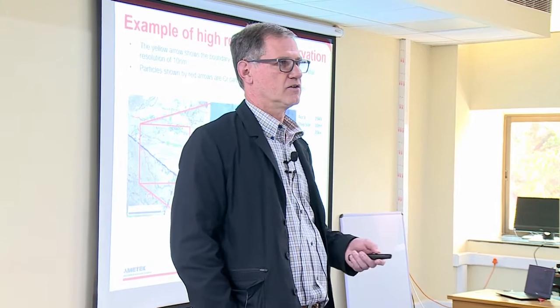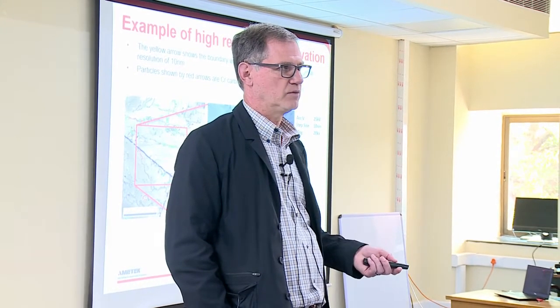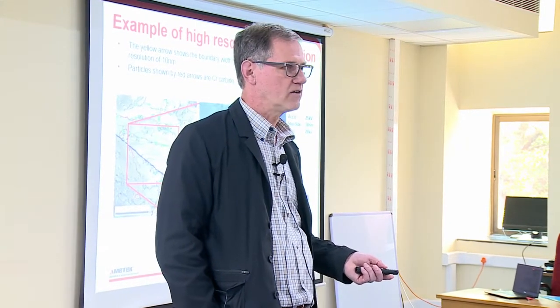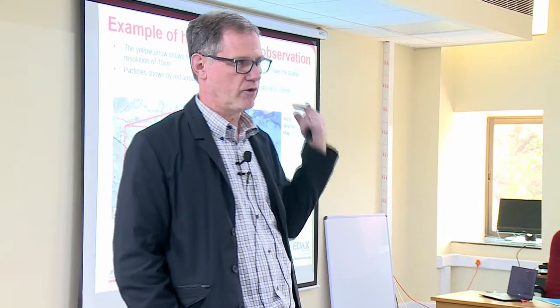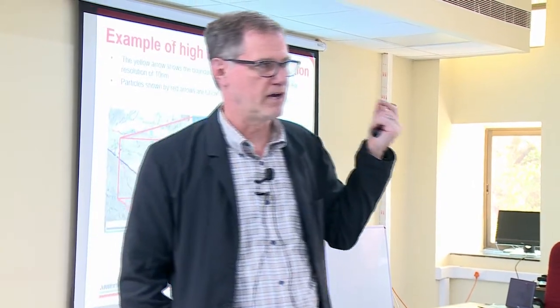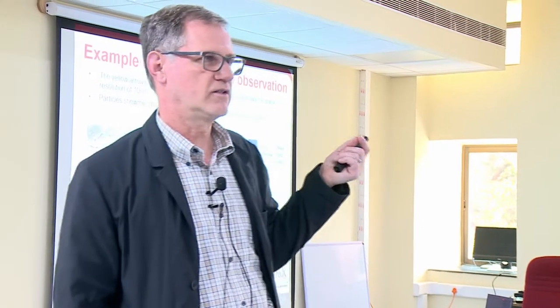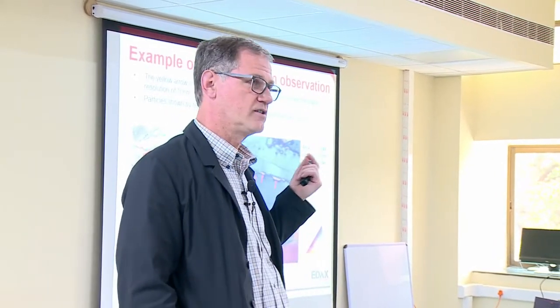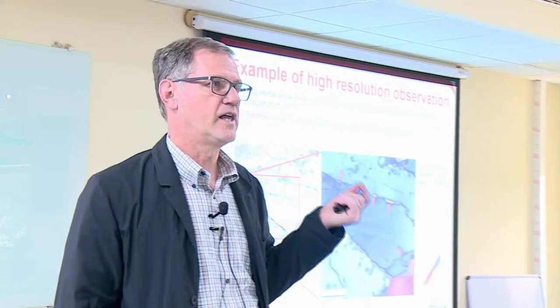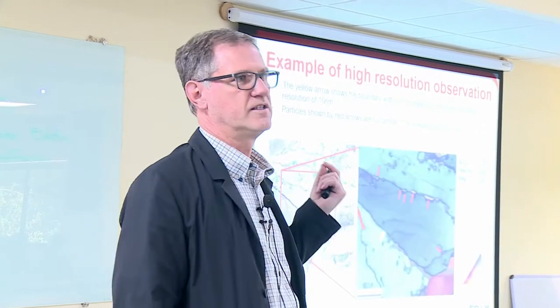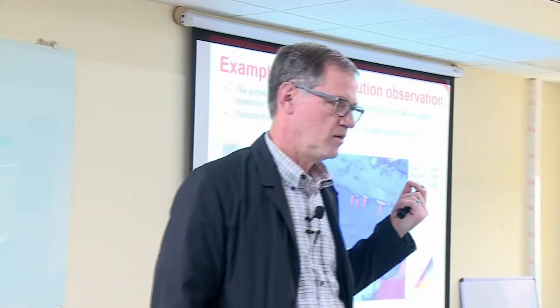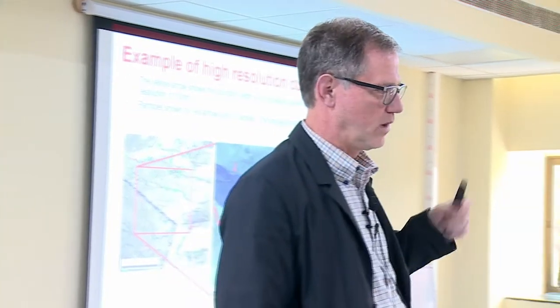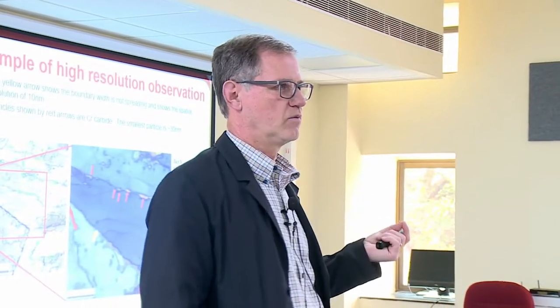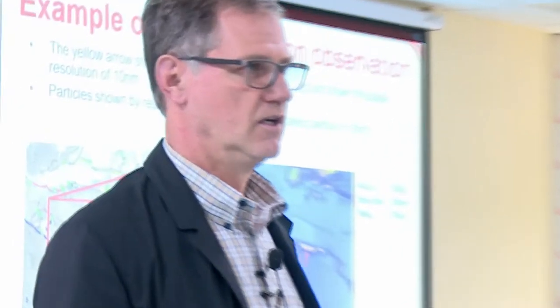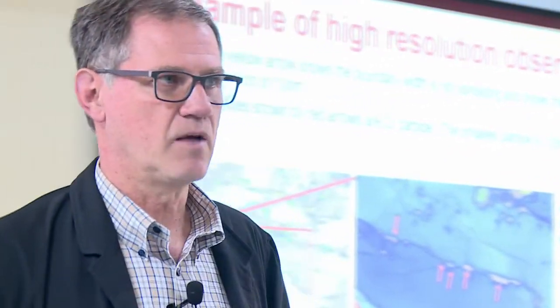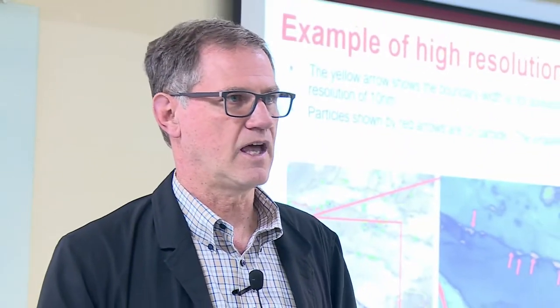There are a lot of signals coming off the microscope. With EBSD, we primarily are looking at elastically scattered electrons, or the ones that are forming the patterns, although we know now better the distribution of electrons and the energies that we're measuring, and there is some inelastically scattered electrons that help form these images. But the images themselves, in terms of the way we interpret them, we basically assume we're only dealing with the elastically scattered electrons. The other signals, like EDS, are coming off the sample, Auger, other things like that.